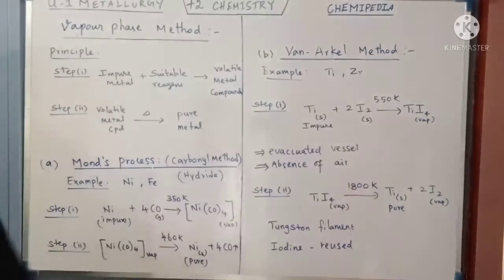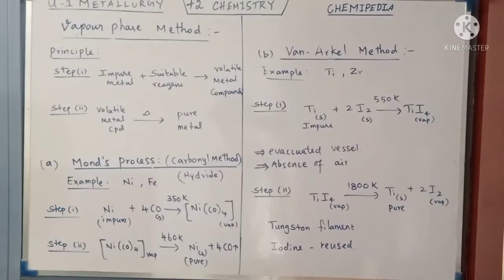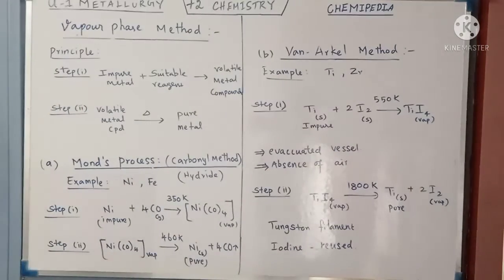Let us see how titanium is refined by the Van Arkel process. The first step: the impure titanium is heated with iodine crystals at a temperature of about 550 Kelvin. Only the metal reacts with iodine, forming a volatile metal iodide — titanium tetraiodide, TiI₄. The impurities remain in a non-volatile state.